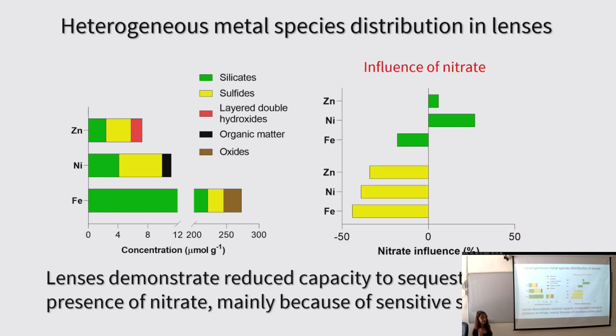Now, how about the impact of nitrate on these species? So here I'm only showing the influence of nitrate for the pools that were present for all three metals. So we're looking at the silicates and the sulfides. We can't really see a specific trend or a specific influence of nitrate on the metal silicates. But for the metal sulfides, you see the same trend where the presence of nitrate or the process of denitrification is resulting in a decrease in the metal sulfide pool, likely due to oxidation of sulfide minerals or the inhibition